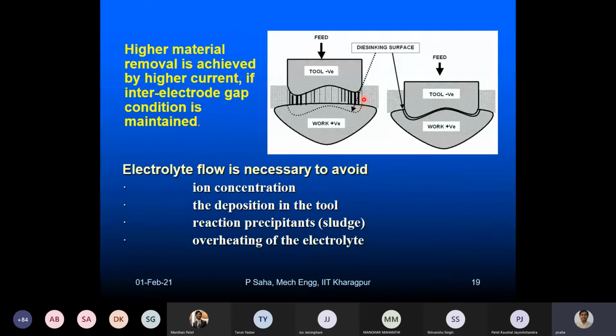So this ferric hydroxide is insoluble. It is dark brown in color. Very fine particles will be generated, and by gravitational force they will settle onto the job, and that doesn't get dissolved. If it remains settled there, the whole electrolyte also becomes turbid, whereas earlier it was clear. Because of the resistance of the electrolyte, further ion exchange at the job surface will also be hindered.